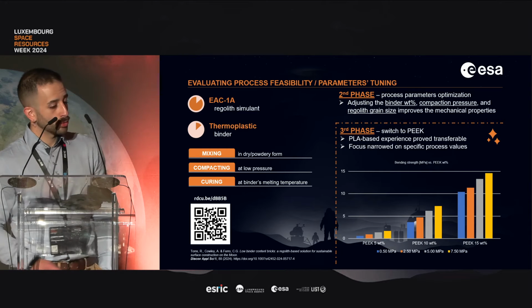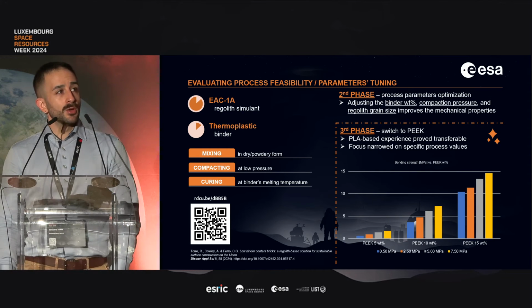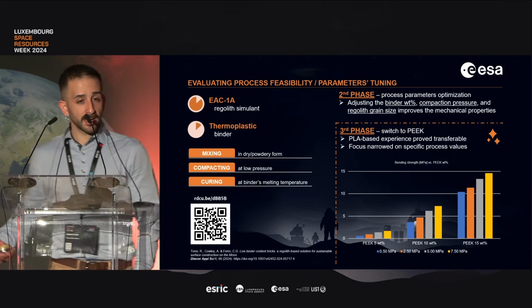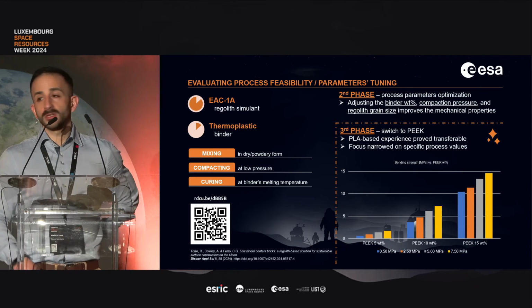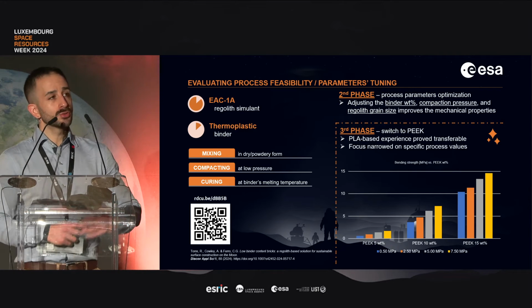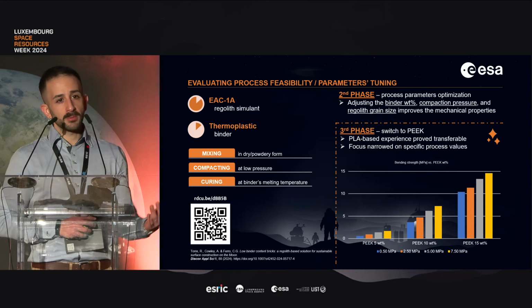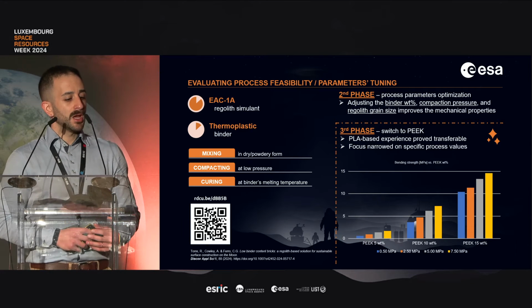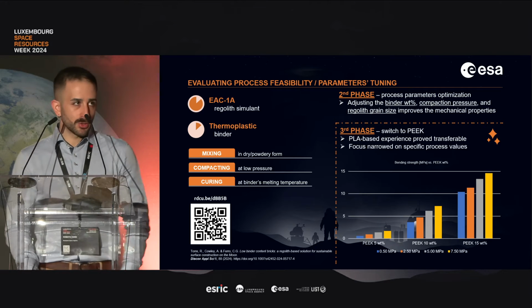So we decided to go a little bit more into the details, and we did an extensive mechanical characterization campaign based on a design of experiment approach. We wanted to see the influence of all the process parameters that we were using, and we found out that the binder weight percentage, of course, the compaction pressure, and the regolith grain size were influencing the mechanical properties, and there was a way to have a set of optimized mechanical properties. We did everything considering the compression strength and the flexural strength as output parameters.